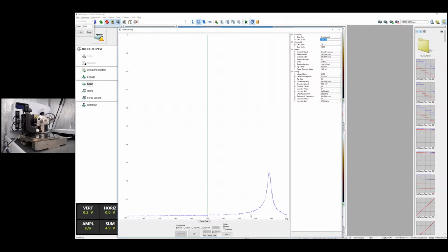Of course, it's not necessary to really use the peak. Even at this kind of relatively flat area, at the foot of this peak, you have already boosted your signal quite a lot. So in the literature, people are still arguing whether you should directly use the contact resonance frequency or use a frequency a bit further away from the actual resonance frequency. So for different kinds of applications, you can choose which one to apply. So let's say I really want to boost my signal quite a lot. I move it very close to the peak location, somewhere here.